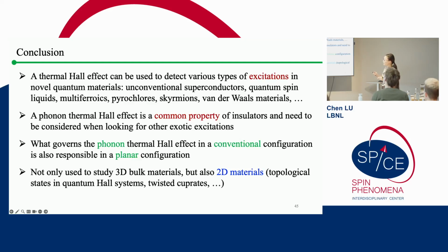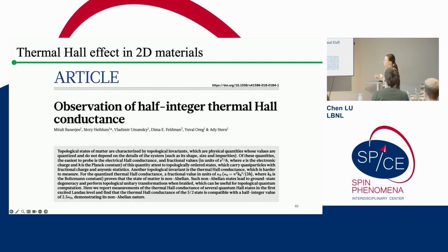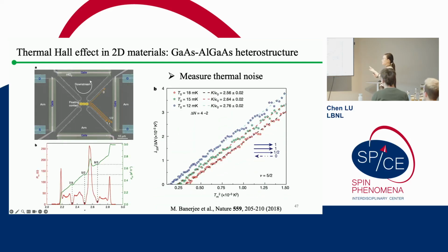Before I end my talk, I want to show you one paper here. It's from Professor Banerjee's group. They observed a half-integer thermal Hall conductance in a 2D system built from gallium arsenide, aluminum gallium arsenide heterostructures. But the one thing I want to emphasize is that in this kind of 2D material, the way people do the thermal Hall effect study is very different from 3D. Basically, there are two completely different techniques.